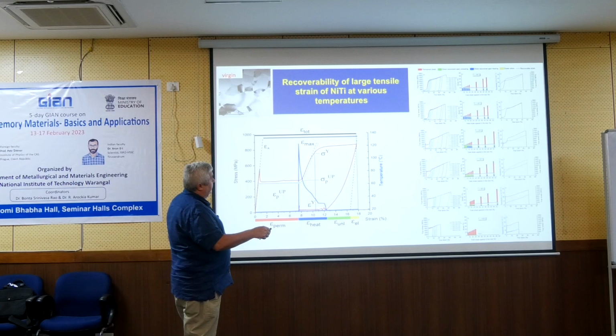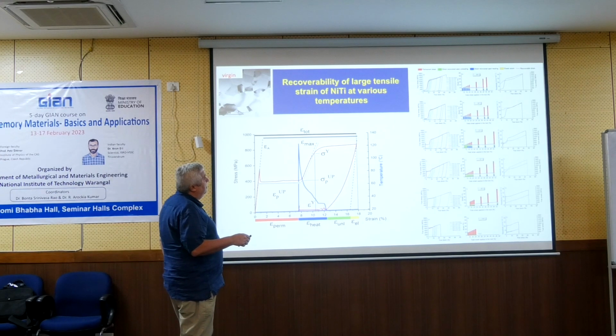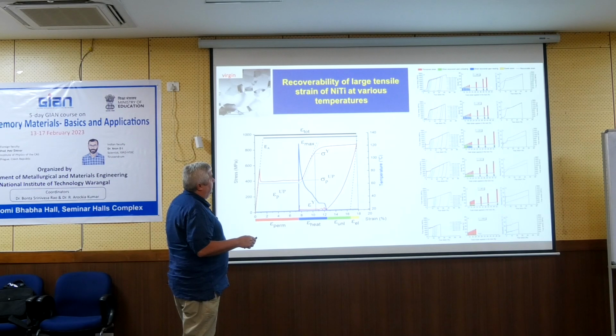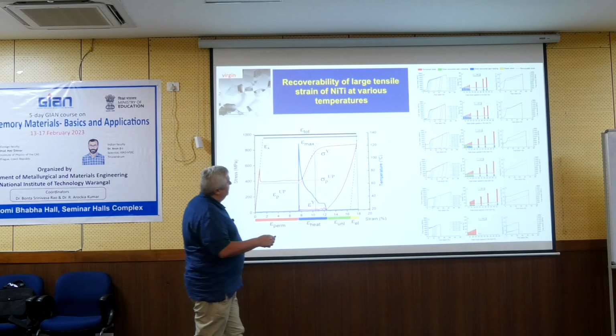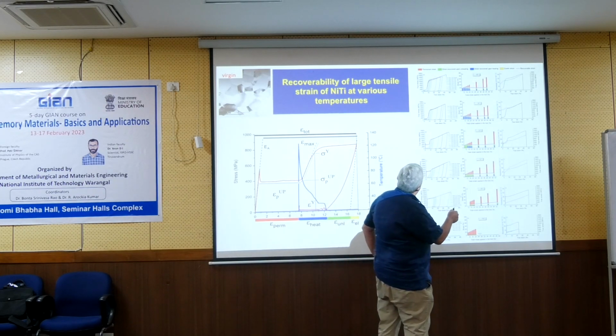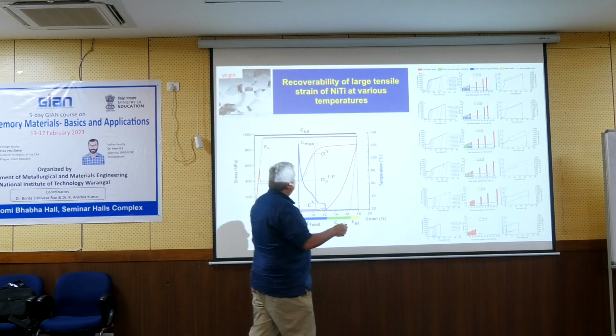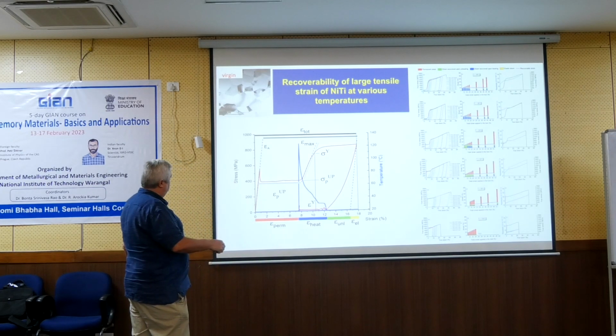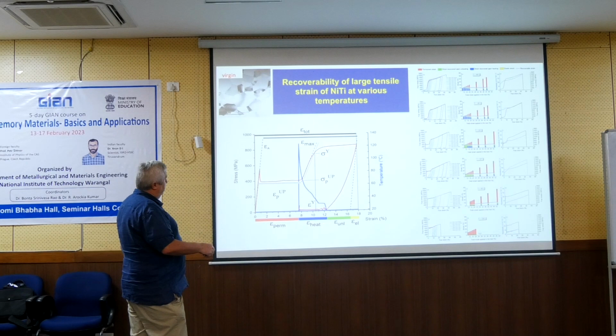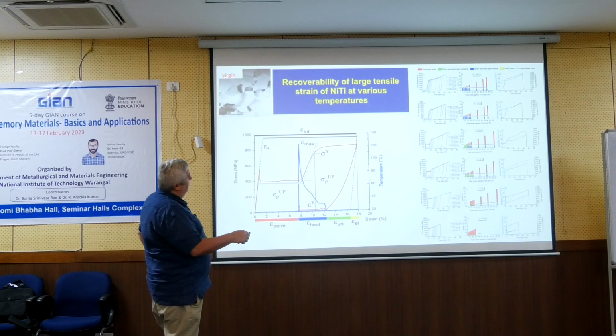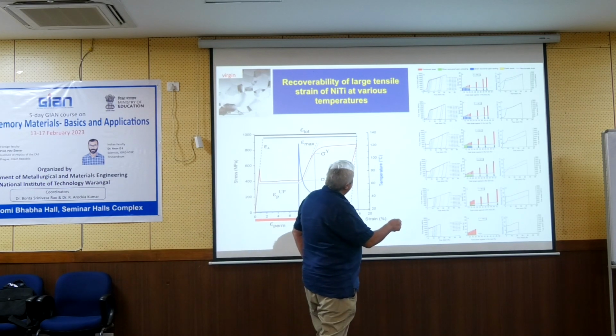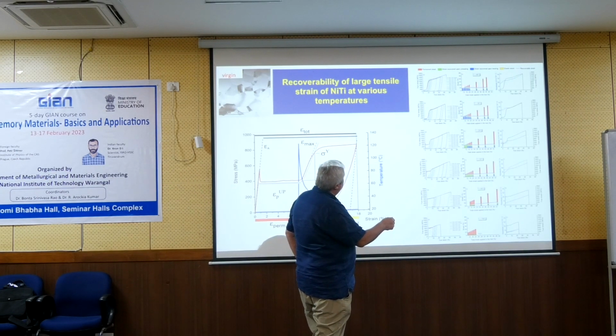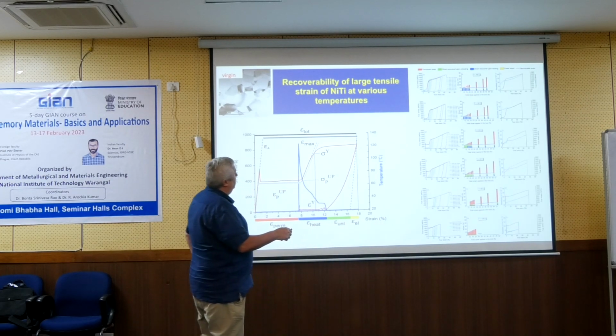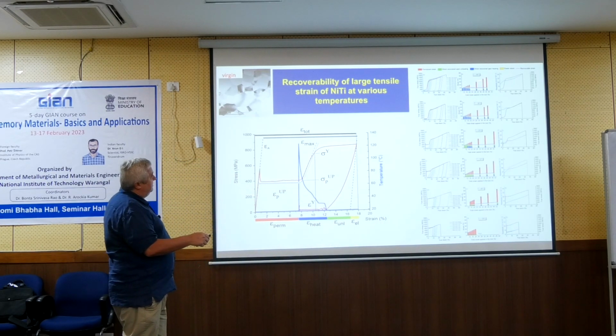Similar figures look like this, but the very important information for me is that this is loading at the lowest temperature, like minus 90 degrees, and you see again the same type of strain. This is permanent strain, and this is the heat. Blue is strain recovered by the unloading and heating. So if you look at it, you have here around 10 to around 16% maximum recoverable strain. This red is unrecoverable.